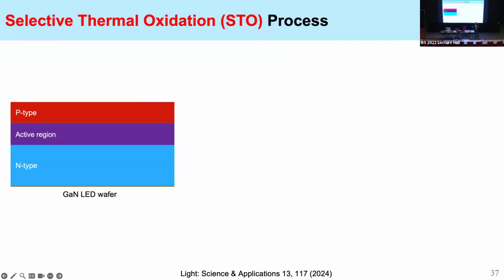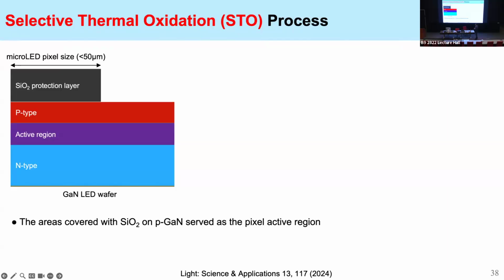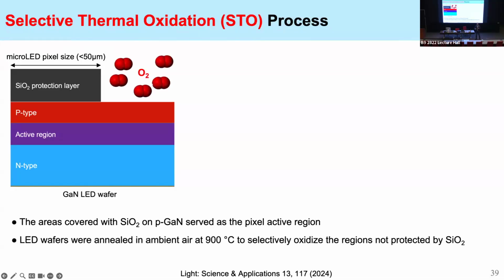Suppose that we start from a gallium nitride LED wafer. An LED is a PIN junction. It has a P-type layer, the active region where the light, the photons, are generated, and then an N-type layer. First of all, we can cover that with a silicon oxide protection layer. The silicon oxide layer is an excellent blocker to keep oxygen from moving into the LED wafer. And then we can put this whole wafer into an ambient furnace, where we have plenty of oxygen molecules.